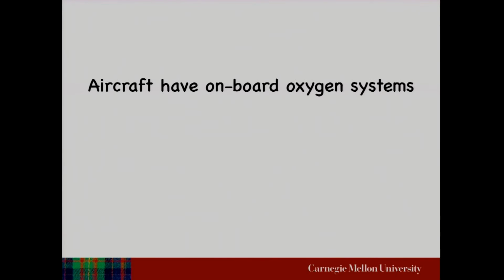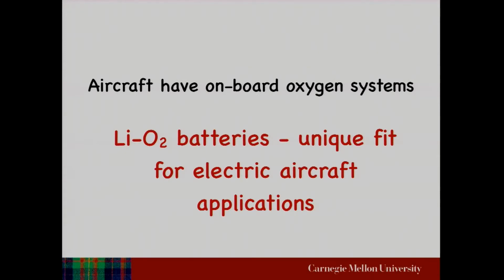And this exploits one of the unique things about aircrafts, which is that aircrafts have onboard oxygen systems. So if you could use the oxygen in an efficient way for the battery chemistry, then you don't have an additional component that you have to add. It can naturally integrate with the way in which the system is already built. And so in this case, it turns out that lithium oxygen batteries, where you use lithium metal that we talked about earlier, coupled with an oxygen cathode, represent a unique fit for electric aircraft applications. This can reach energy densities of about 400 to 500 watt-hours per kilogram, accessing the general aviation market. So you could think about electrifying planes that fly between 200 to 400 miles, which represents 90% of the flights that are taken today.